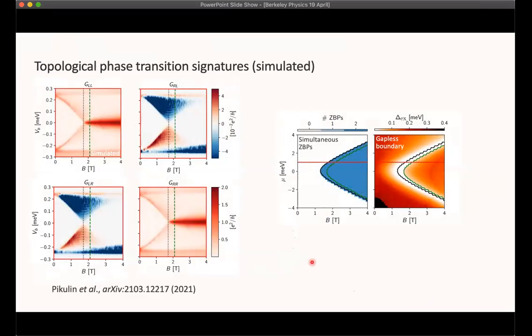So to recap, what I'm proposing is that in order to convince ourselves of a topological phase transition, we should take a page out of the work from the Zurich group with the Haldane model, and we should map the closing of a gap. And in doing so, following this red line in these phase diagrams here, which is exactly the increasing magnetic field in this simulation, we expect to see a boundary of the topological phase that is gapless, followed by the presence of not one, but two zero bias peaks in our spectrum. And this will give us very strong evidence that we've entered the topological phase, and we can furthermore map more of the phase diagram to give us stronger evidence.